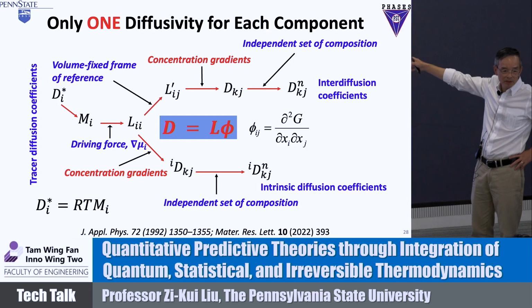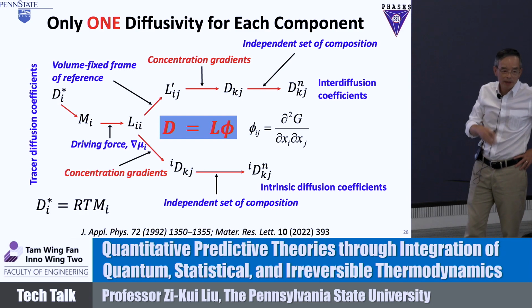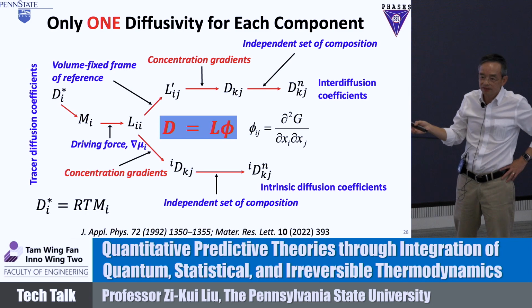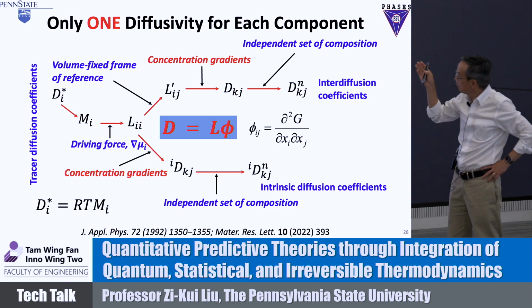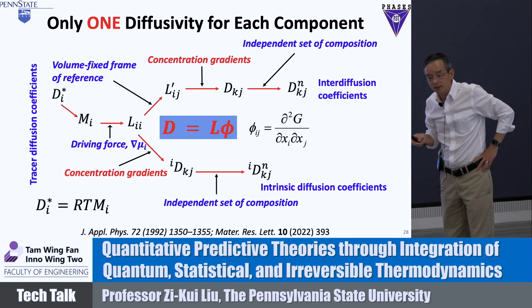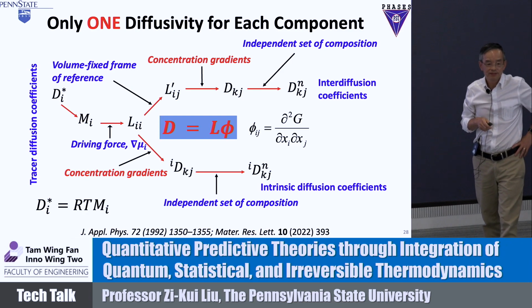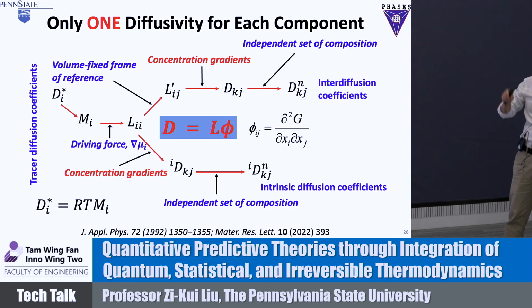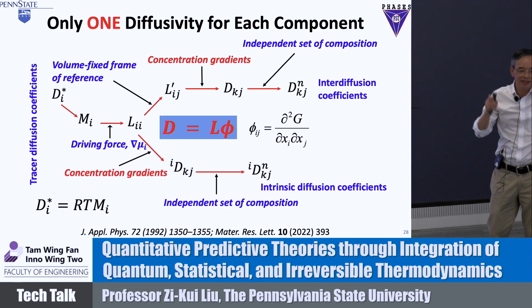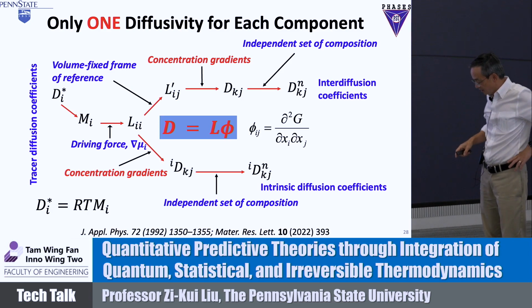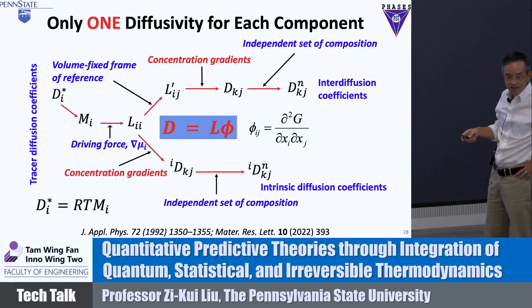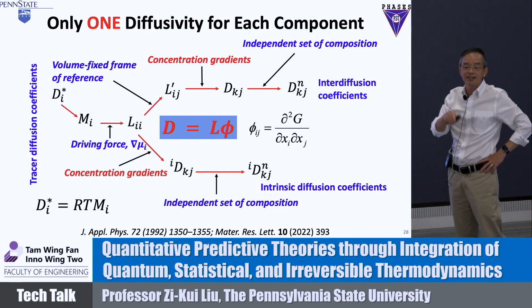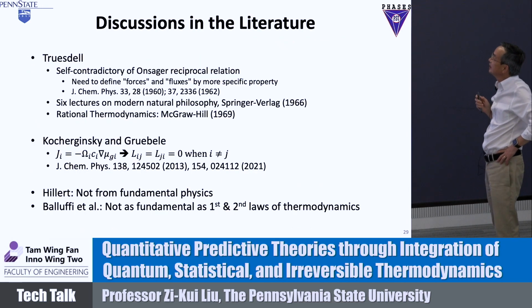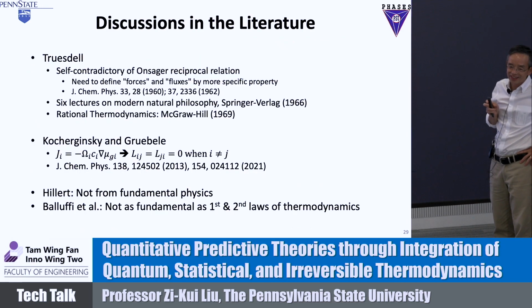So all those parameters, we call them kinetic parameters. Even people have this Maxwell matrix. They are all derived from one diffusivity times the thermodynamic factor. So all the diffusivity is kinetics plus thermodynamics combined together. But the kinetics is only one parameter. So that convinced me. That means all those matrices people talk about in Onsager thermal diffusion are a thermodynamic factor times another kinetic factor. All right. So of course, I'm not the only one to question Onsager, right?